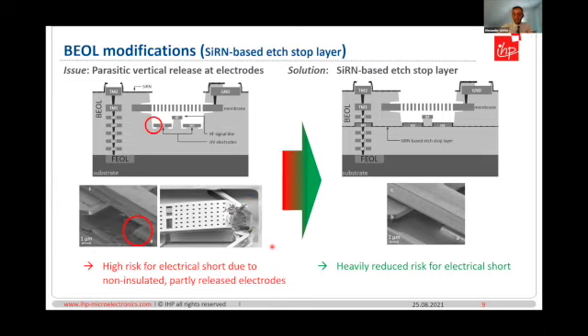To prevent this, the solution is a silicon-rich nitride-based etch stop layer, which is located on metal 4 here in the schematic. And this heavily reduces the risk for an electrical short. You see this also here in this tilted SEM image. There's no underetch.